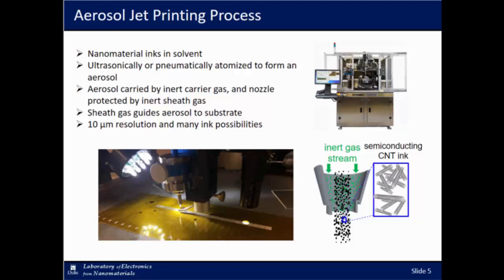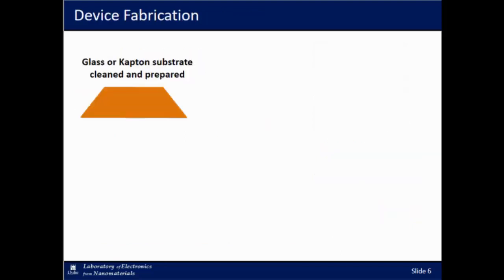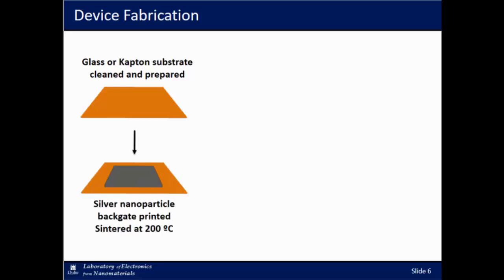And with this printing process, there's also a bunch of different parameters that we can change to optimize different inks. So we can change the sheath gas flow rate, the atomizer gas flow rate, or even the ultrasonic energy that excites the ink to give us different properties. So for these devices specifically, we start with either a glass or a Kapton substrate. We clean and plasma ash it to prepare for the ink deposition.